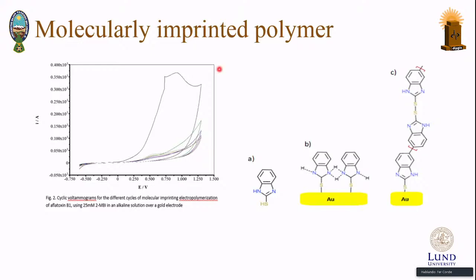In the case of molecularly imprinted polymers, we use mercaptobenzimidazole as the main molecule, as the monomer. Here we use electropolymerization, which was performed over the electrode, with the formation of disulfide bonds between these monomers. And as we can see here, in every cycle of cyclic voltammetry, the elongation of the polymer is set. We must emphasize that this molecularly imprinted polymer is acting as the insulating layer and also as the biorecognition element.